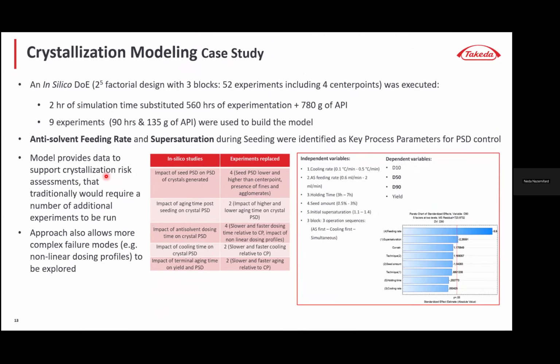Now, as I said, we use this model to help us understand this crystallization. As you can see here, we managed to do a full factorial design in silico, with a fraction of the experimental time and material that would have been taken to do the same amount experimentally. The model identified two key process parameters that really mattered for controlling the particle size: antisolvent feeding rate and supersaturation level during seeding were critical levers that we managed to understand through this in silico DOE. Things like holding time and cooling rate had negligible impact on the particle size distributions. So by using the model, we could focus on what mattered most very early in the process.